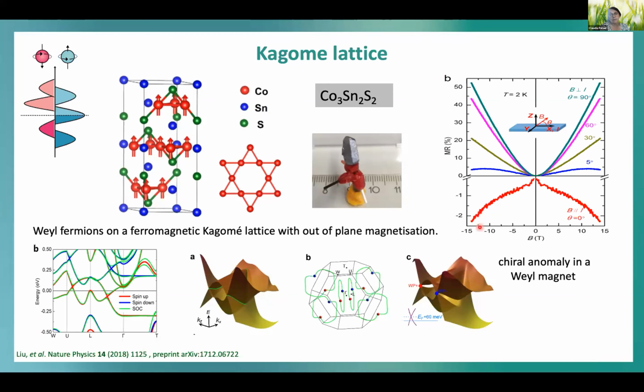So you have a negative magnetoresistance if the B field is in the direction of the current, and a positive magnetoresistance if it's not. It has the Weyl points, and also a very simple band structure. As I said, it's a half metallic ferromagnet—you see only one spin direction, if spin is a good quantum number, which it's not in the case of spin-orbit coupling.